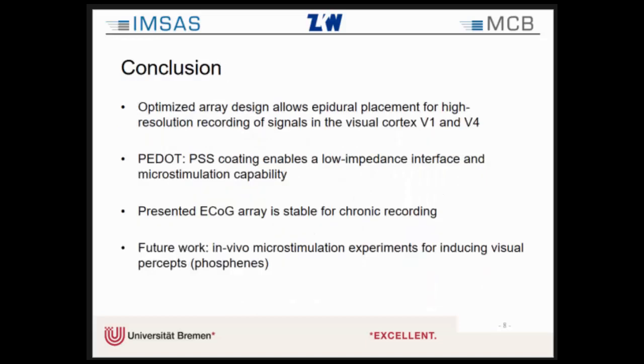And with that, I would like also to conclude that we designed an optimized array for placement on the visual cortex to cover V1 and V4 simultaneously. Our PEDOT-PSS coating enables us a low impedance and gives us the capability for microstimulation. We also showed you that the presented ECoG array is stable for chronic recording of the activity, and of course the next step is that we are now going to do the first microstimulation experiments to evaluate the capability to produce phosphenes directly in the brain. And with that, I would like to thank you for your attention.